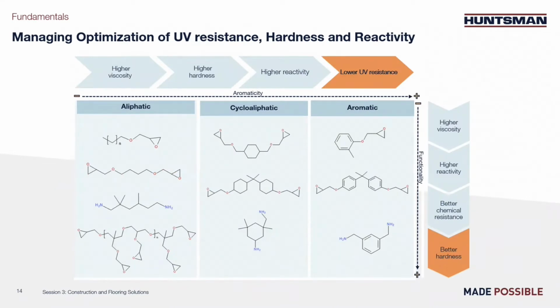So there is a way to reduce UV absorption by playing with the epoxy molecule or amine we are using to design an epoxy matrix. We have drawn different molecules, and the two left columns are aliphatic or cycloaliphatic molecules, which are in principle not absorbing UV. Generally, those molecules lead to lower viscosity, hardness, and reactivity. If lower viscosity is an advantage, lower hardness and reactivity are really a problem.